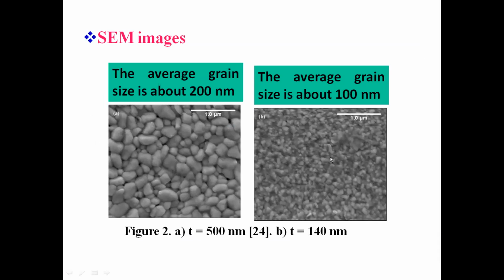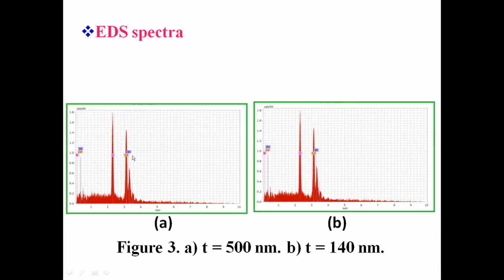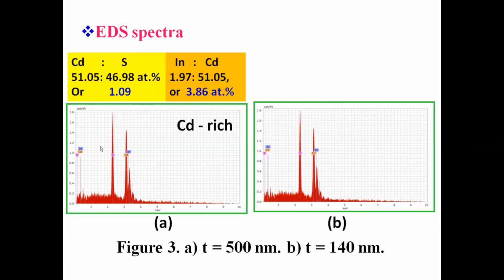Here are the EDS spectra for the two films. The films contain cadmium, sulfur, and indium. Now the ratio of cadmium to sulfur in this film, which is the thicker film, is 51.05 to 46.98 atomic percent, or 1.09. This means this film is Cd rich. The ratio of indium to cadmium in this film is 1.97 to 51.05, or 3.86 atomic percent.